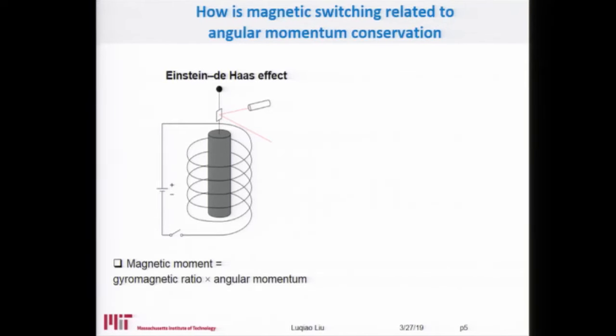Actually, this was first discovered and verified by Einstein a long time ago. And people say this is probably the only experiment that Einstein has ever done. Basically, he tried to magnetize a magnetic bar. While he magnetized this bar using this circuit coil, he found that while the magnetic moment gets switched, the physical piece of this magnetic block also gains some angular momentum. That means it starts to rotate. So in order to switch the magnetic moment, it has to gain some angular momentum from somewhere else. In this case, it gains the angular momentum from its physical rotation. So in the end, the total angular momentum is conserved, including both the magnetic part and the physical motion part.